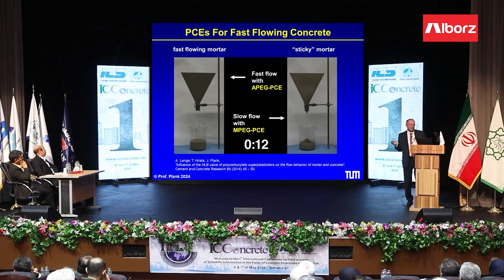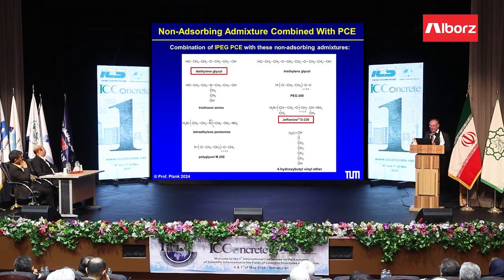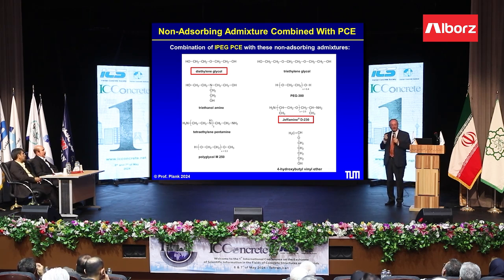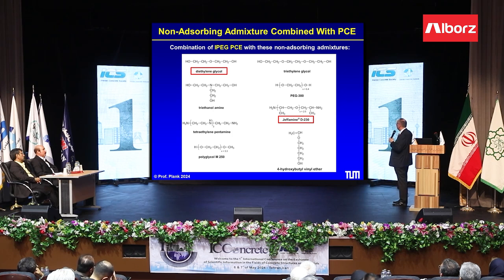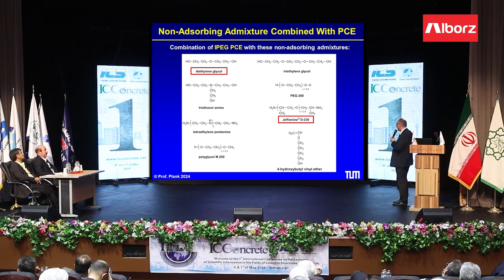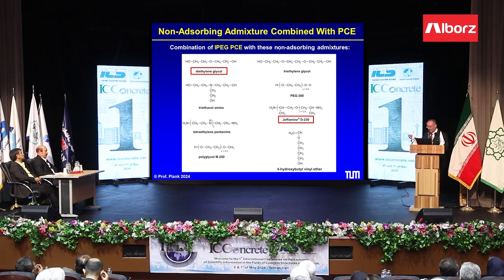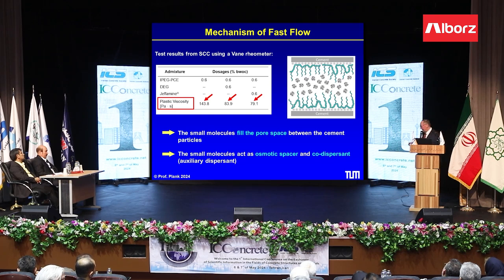But like I said, in Germany, we use a lot of MPEG PCE. So the question was, how can we also improve the MPEG PCE? And the solution we found is if we combine the PCE with a small molecule alcohol, a diol, for example, very simple diethylene glycol or triethylene glycol or PEG 300, some diols, then you improve the flow speed of concrete very much, and even some amines which we use as accelerator work. So by formulating a PCE solution with these simple alcohols, it's possible to increase the flow speed.